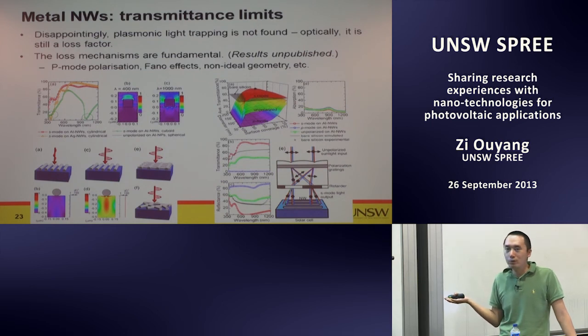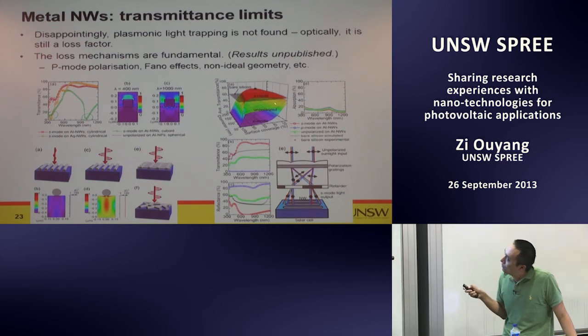Actually, other people use this as a polarizer to block the light as you wish. So we think, no. So in the end, we get unpolarized light like this. This one is bare silicon. So it's always decreased because of the P mode. So we think, if we only keep the S mode and get rid of the P mode, we may have very, very high enhancement compared with the bare silicon.